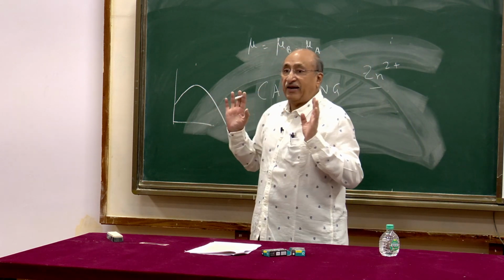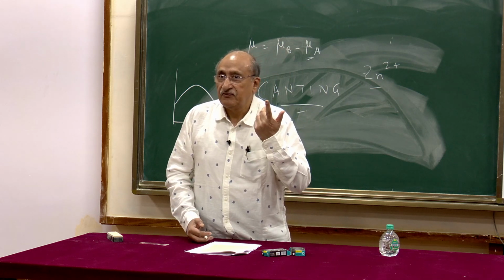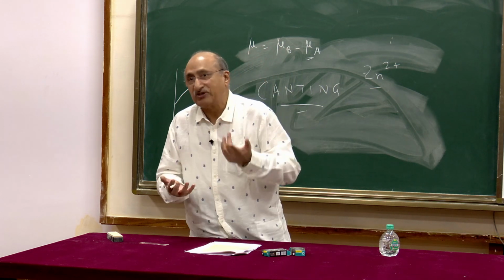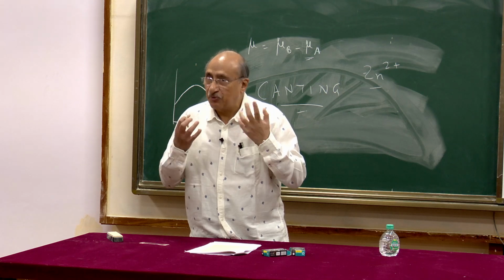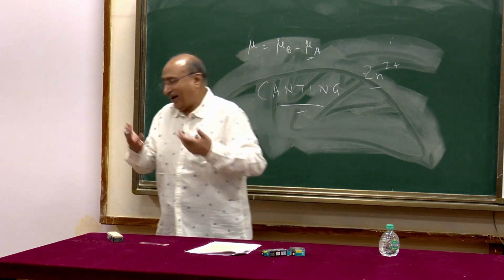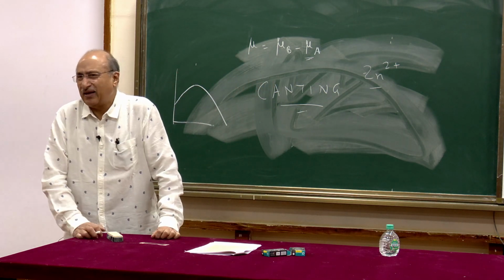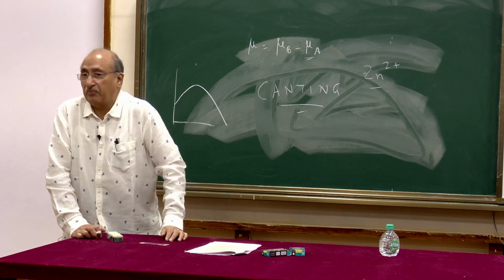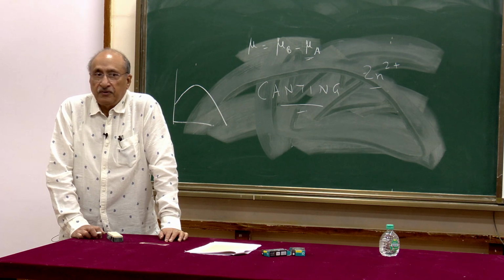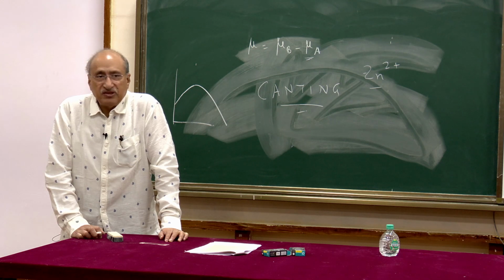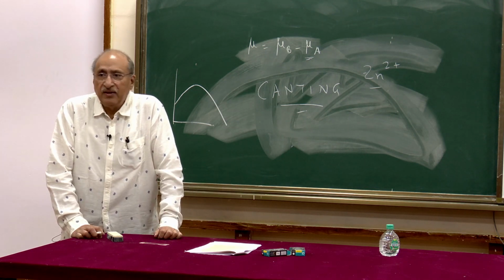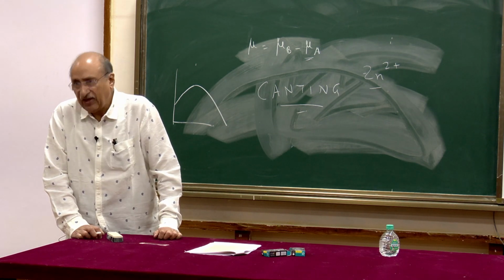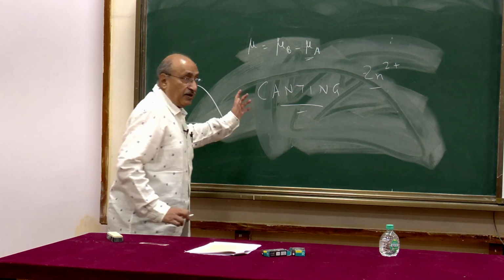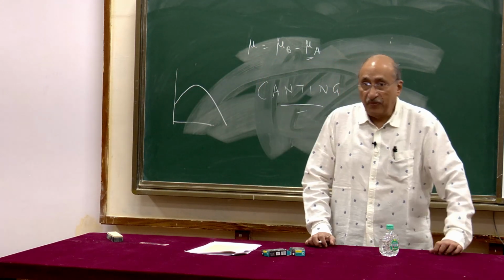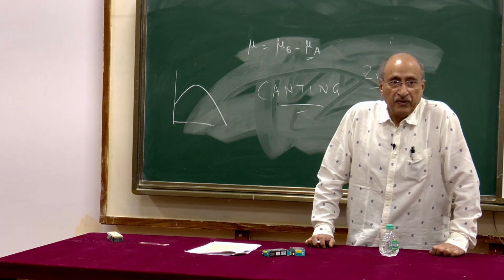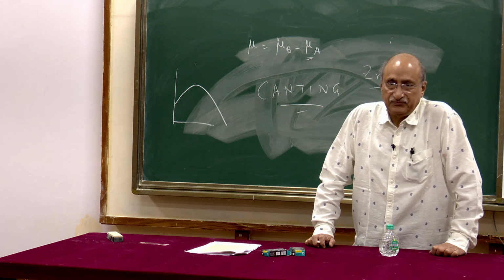Then the only exchange interaction which is there is BB, which is antiferromagnetic in its own sense. Therefore, pure zinc ferrite is supposed to be non-magnetic, or rather antiferromagnetic with a very low Néel temperature. It has a Néel temperature of 4 or 5 degrees Kelvin, I don't remember. There is a lot of interest because we have seen, in our own group, that if the same material, zinc ferrite, is made in thin film form or nanocrystalline form, it becomes magnetic.